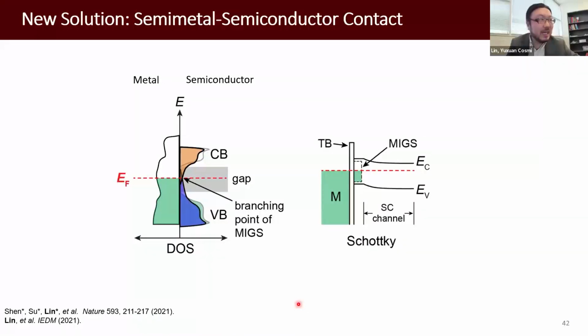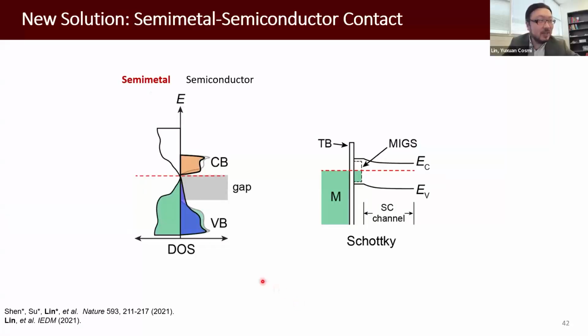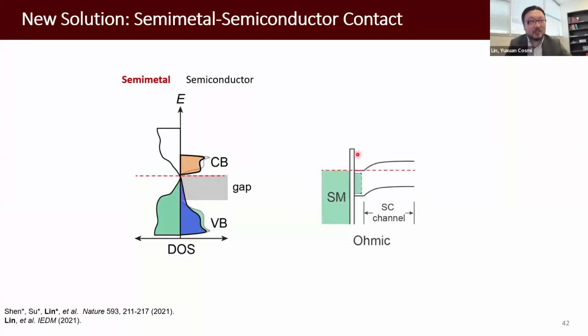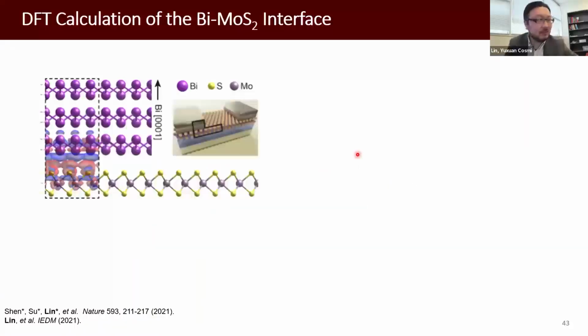So in order to deal with that, we developed this semi-metal contact. We replace the metal with a semi-metal like bismuth, antimony, etc. They have a lower density of states in a certain energy range. If they have good alignment with the band edge, then the metal-induced gap states from that energy range are also much smaller, and we may have enough electrons to fill all the states. Then the Fermi level can be pushed to the conduction band edge.